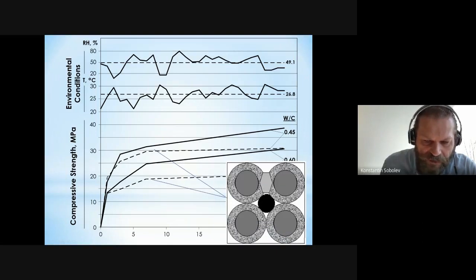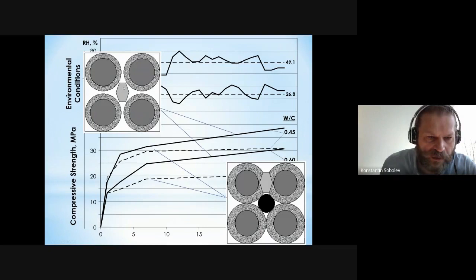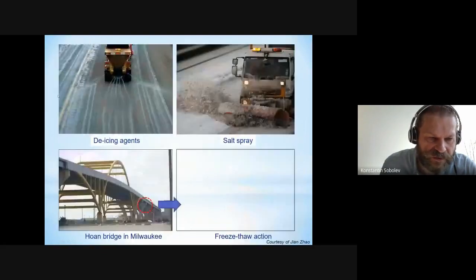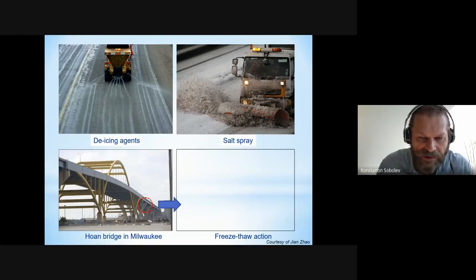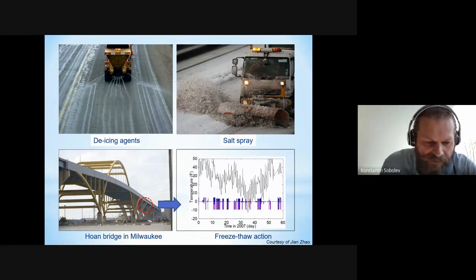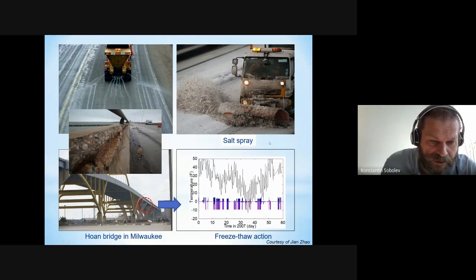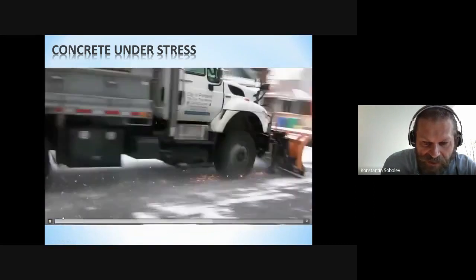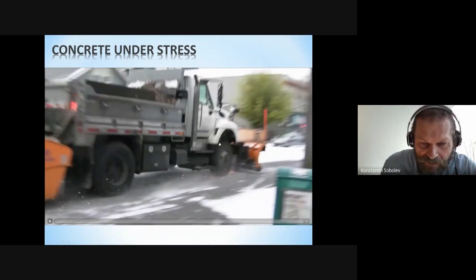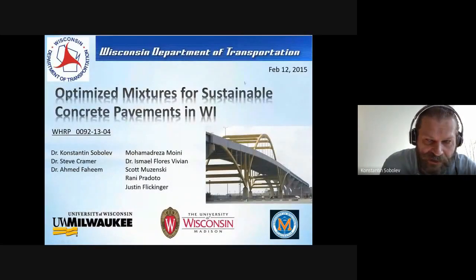And this is because of rapid drying and poor microstructure, while under perfect moist curing conditions, you form a very beneficial microstructure. And if you apply de-icing chemicals, if you use salt spray, and you have all these de-icing operations, obviously you have freezing and thawing cycles, which we have about 50 per year in Wisconsin. You have premature failure of material. And in addition to this, you can see that concrete is subjected to different forms of mechanical action, especially on the pavements here.